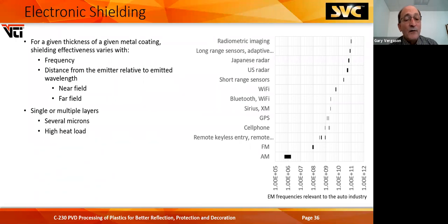Electronic shielding coatings are a little thicker. It depends on the frequency, the distance from the emitter relative to the emitted wavelength, whether you're near field or far field. It can be a single layer, like a thick layer of aluminum, or multiple layers, several microns in thickness. With sputtering, you can have a relatively high heat load. The chart on the right shows the different frequencies for everything from AM radio to radiometric imaging.